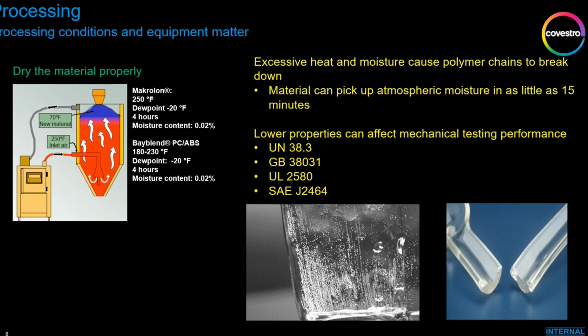Same thing with drying. So we all probably understand that plastic materials need to be dried before molding, and this is a critical step. They tend to pick up atmospheric moisture during transport, and they need to be very dry before molding. Typically, for polycarbonate blends, you need to be at 0.02% moisture. That's a pretty low number. You need really good equipment to achieve that.